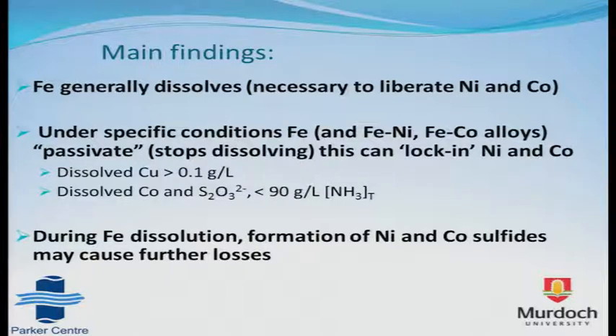And there's another aspect which may be affecting the efficiency of the process, and that's that during the dissolution of iron, there's this formation of the sulfides, since the thiosulfate acts as an oxidant and is reduced by the iron and can form nickel and cobalt sulfides, which in itself cause further losses as they don't remain in solution.